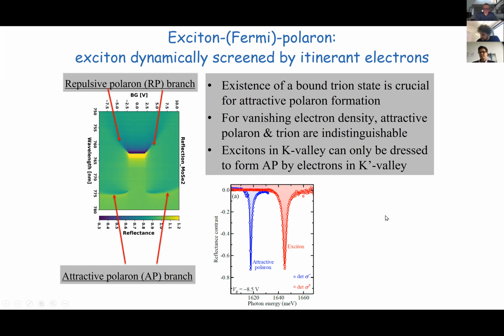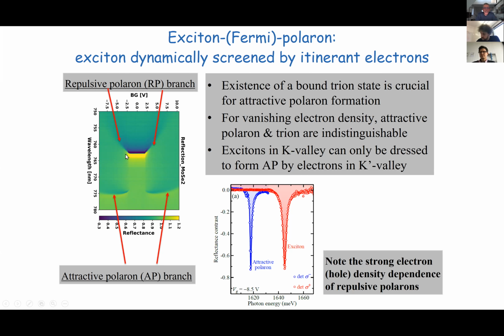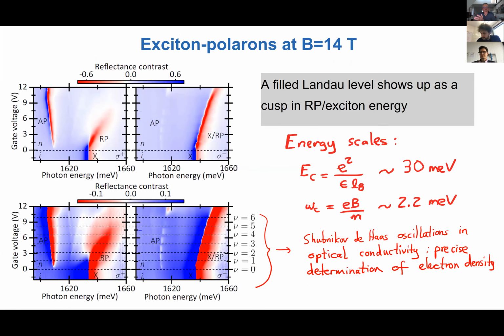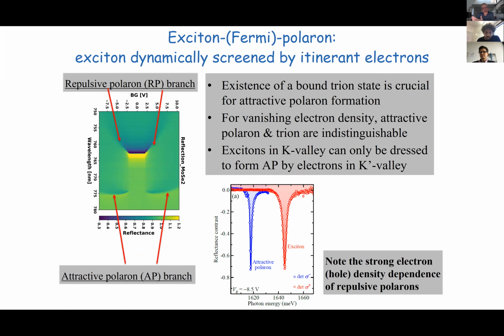Okay, but the more important effect for this talk is that even though the attractive polaron has a non-trivial and relatively weak energy dependence on the electron density, the repulsive polaron shifts very abruptly as we change the electron density. And this provides a fantastic tool to monitor what is happening to the electronic system. Okay, so before I do that, you could also wonder, we put in electrons and we need to find out the electron density. How do we determine this?